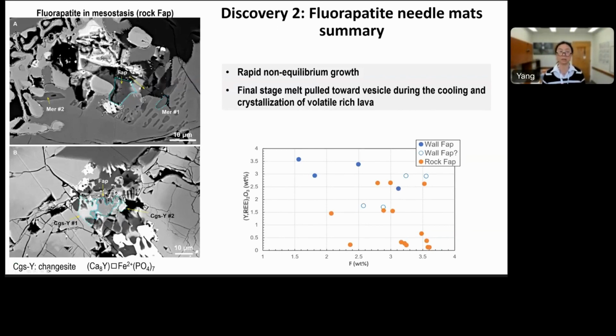So as a summary, we think those fluorapatite needles are non-equilibrium growth out of the latest stage melt. And then the final stage melt was probably pulled towards the vesicle because the vesicle would have lower pressure than the equilibrium pressure inside the rock. So when it was pulled towards the vesicle, those needles quickly formed and formed this kind of pattern. I think this morphology has not been recorded before, so it's interesting to see what happens when the lunar basaltic lava almost fully solidified. There are a lot of things happening, which is kind of eye-opening.